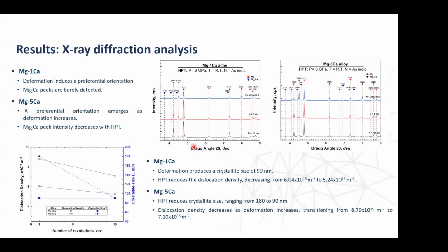And we see the dispersion of the magnesium two calcium, and this is shown by the gradual disappearance of the magnesium two calcium peaks by XRD. And we did calculate crystallite size and defects from these materials, and they are, of course, well deformed microstructures.